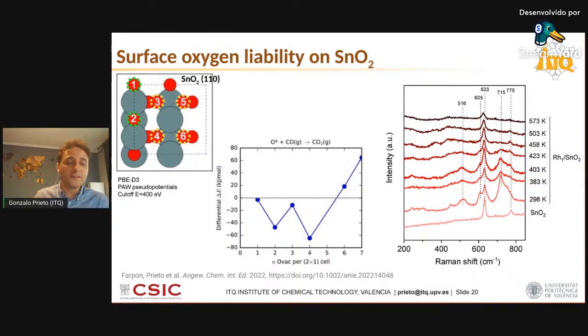Again, here we were benefiting from the bulk of information that exists on tin oxide in other scientific areas such as sensing, where surface oxygen vacancies are essential ingredients for functionality. So what we concluded from all this investigation was that it was very easy to lose bridging type of surface oxygen on these materials, much easier on tin oxide than it would be on ceria and certainly on zirconia, where generating oxygen vacancies on surfaces is energetically very, very demanding.